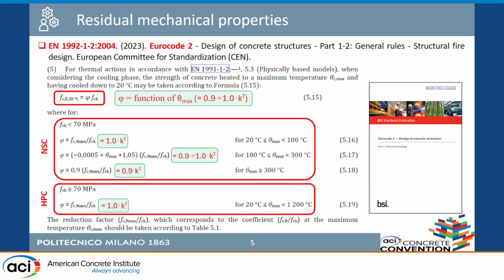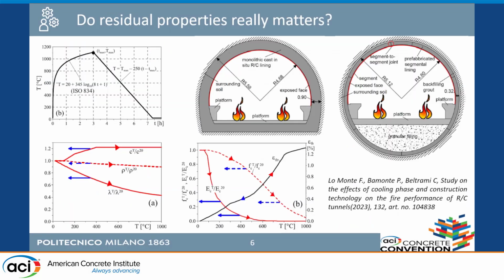This is quite tricky, especially for structural analysis, because in structural analysis, the properties in any point of the material do not depend anymore on the actual temperature. So at 5 hours, the temperature is this one, so I know what is the compressive strength. No, because I need to know what was in that point the maximum temperature reached. This, for the structural analysis, is much more complex, because so far there is no software that allows to perform this kind of analysis. So here, just to show the analysis that we perform comparing two structural solutions for a deep tunnel, we implement a routine in Abaqus in order to make the properties of the material depending on the maximum temperature reached up to the moment of analysis.